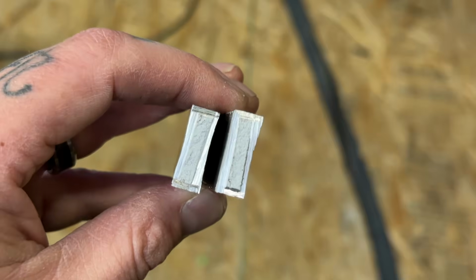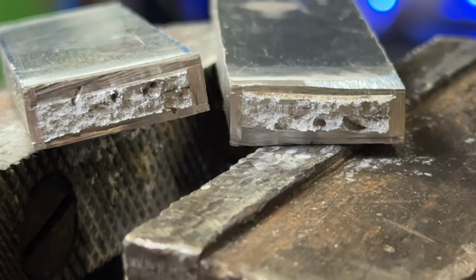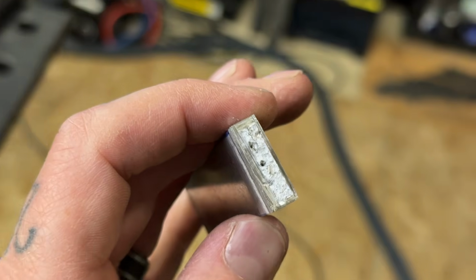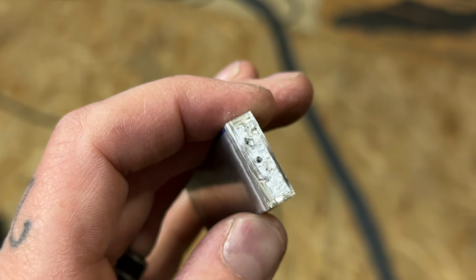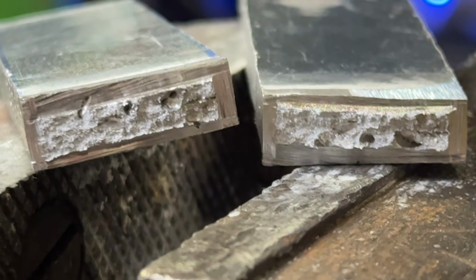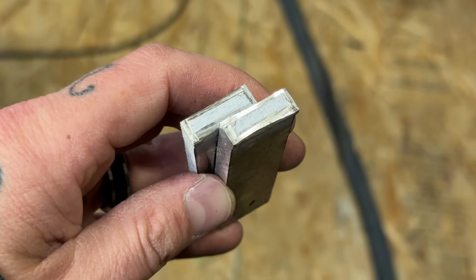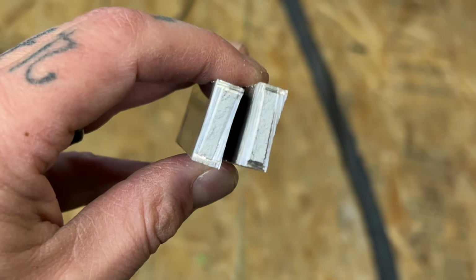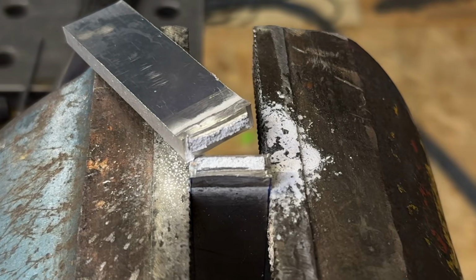Sometimes if there's problems with the welding, you can see something like this here. We can see that there's areas of lack of fusion. We can also see there's little pockets of porosity here and there. This test is a great way that you can take a look at the inside of your welding piece to see how you actually did to get all the way through the base material.